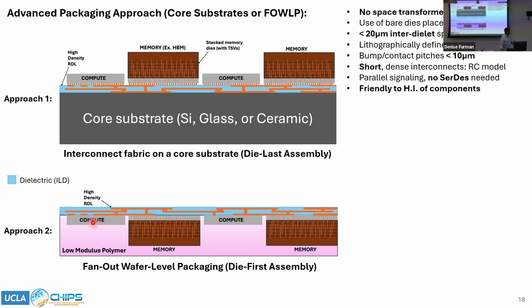In the second approach, called a reconstitution approach, you take these bare dies and embed them in some kind of molding compound, which usually has to be a low Young's modulus polymer. Then you build up the wiring on top of that, and this building up of wiring is called a redistribution layer. In this case, the wires are lithographically defined, and they are again built using some kind of back end of line process. You can clearly see in this case, because you don't use packaged components but bare dies, and there's a high interconnect density on the substrate itself, you don't need any space transformers. You directly use bare dies. And because you use bare dies, you can place these chips very close to each other. In fact, you can get less than 20 micron inter-dielet spacing.